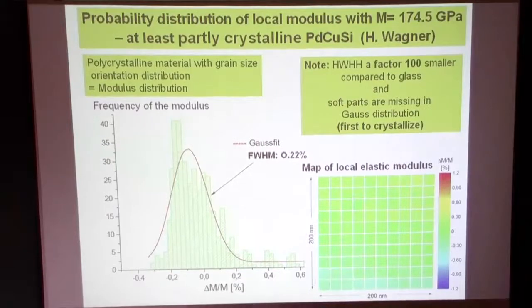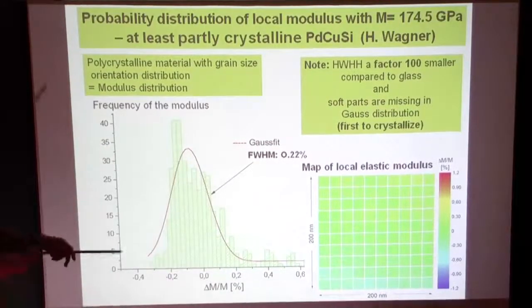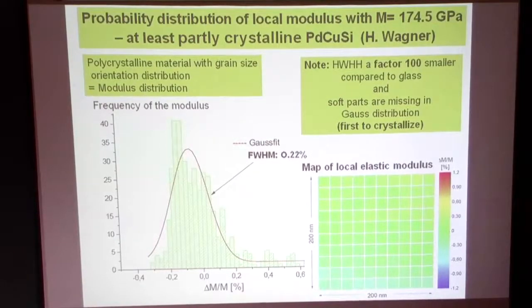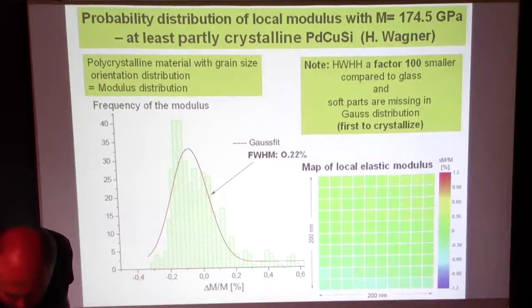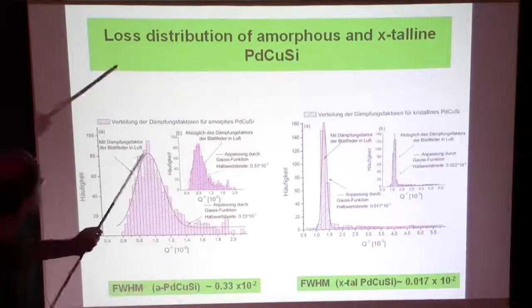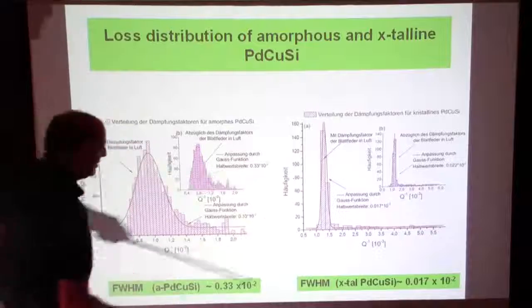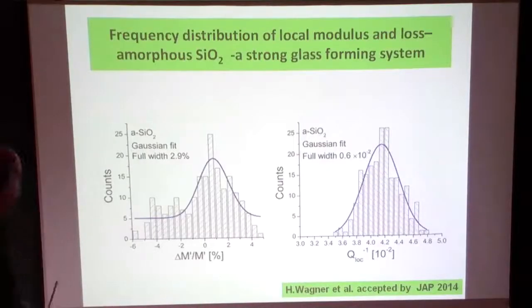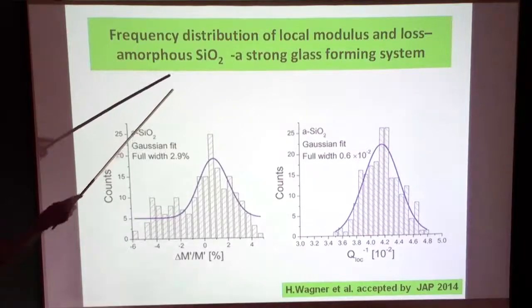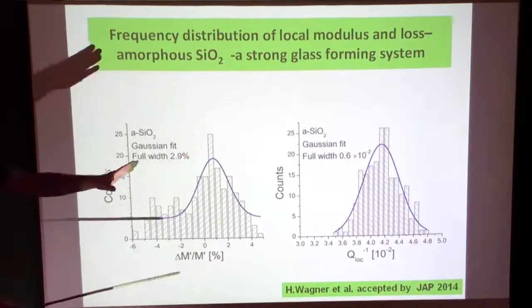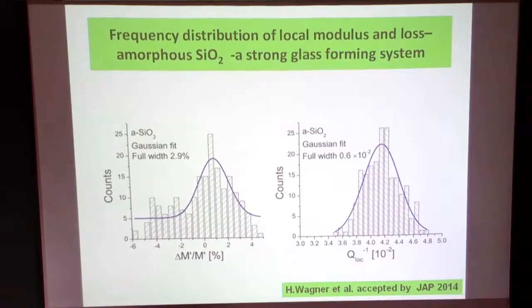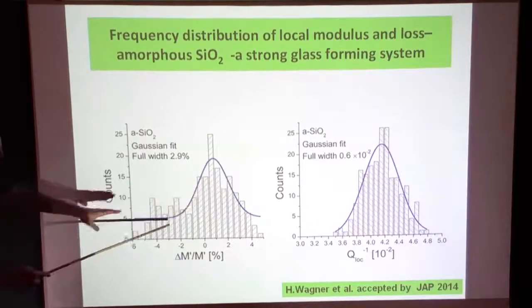So in the landscape picture, I will draw it again later maybe, we have a very small width obviously for the crystal, only 1 point in a single crystal in the landscape, 1 minimum, but a meta-basin in the amorphous one, a broad distribution. And I bring it up only, this is the loss distribution also. The losses are very broad compared to the crystal, and that's new work actually in this area is silicon dioxide. This is a strong glass, so bond oriented, which means that you cannot have such a distribution of different configurations. And so the width actually shrinks down to 2.9% if it is really Gaussian.